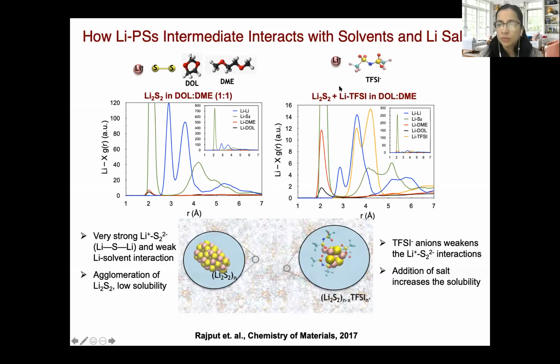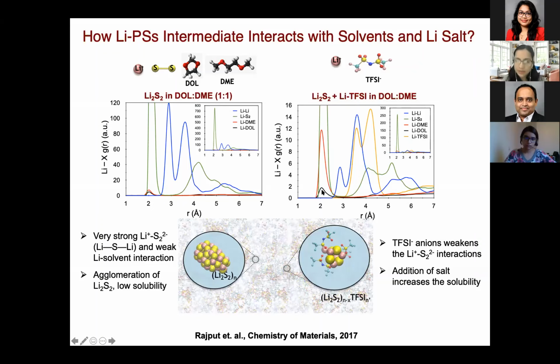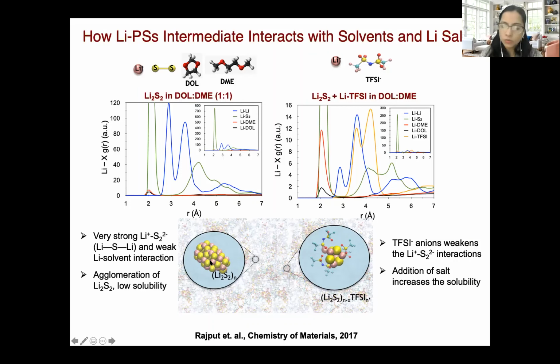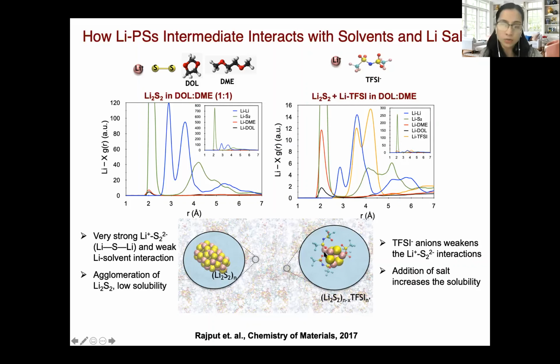So we added 1 molar LiTFSI into the same system, and we observed a significant change in the solvation structure. We still observed a strong lithium and polysulfide interaction, but we noticed that now there is an increase in lithium solvent interaction. And that's coming because of the competing interaction from TFSI and polysulfide to bind with lithium. This competing interaction disrupts this polymeric structure and allows more solvent molecules to bind with lithium, which increases the solubility of these lithium polysulfide species, Li2S2.